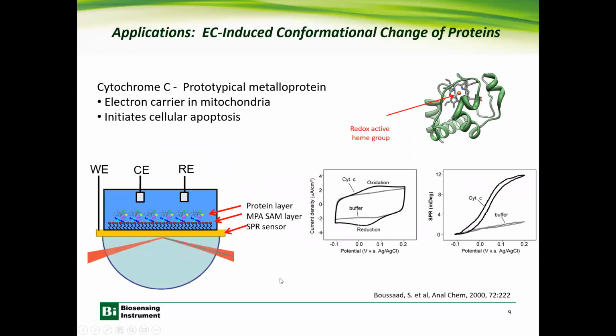So now let's look at the first one. This example shows the conformation changes of a protein, cytochrome C. And this one has this heme group, which can be reduced or oxidized by controlling the potential. First of all, when it's attached to the surface, it will have a typical SPR angle. And then by using electrochemistry to either oxidize or reduce the heme group, so controlling the redox state of the heme group, this molecule either opens up or closes in, so it changes its conformation. And this conformation change will change the physical state of the interface, and correspondingly it will be measured by the SPR.